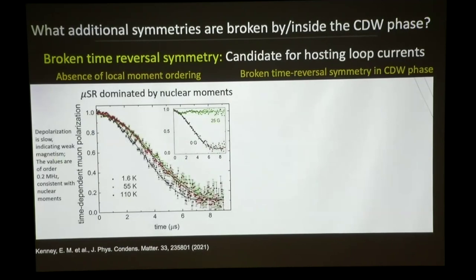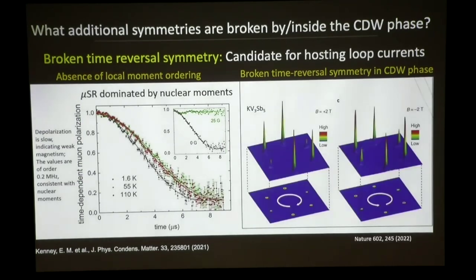But the more interesting thing is that the charge density wave also breaks, at least by some measurements, time reversal symmetry. So this material has no magnetic moments. And you don't have to understand this. All I can tell you is that these are muon, mu SR measurements. And you can see that there are no spins in the system, no isolated spins. And yet, the material breaks time reversal symmetry.